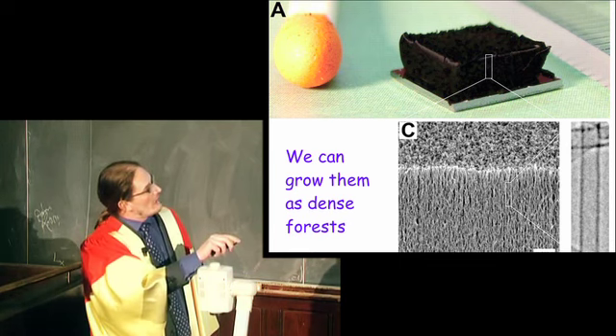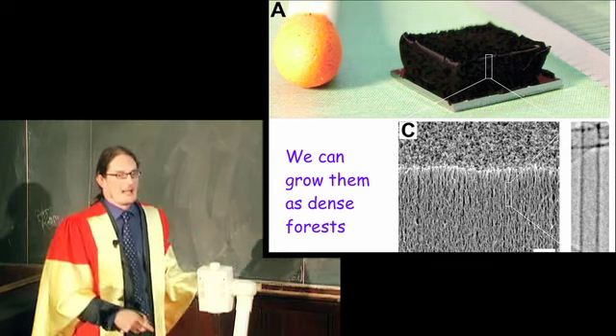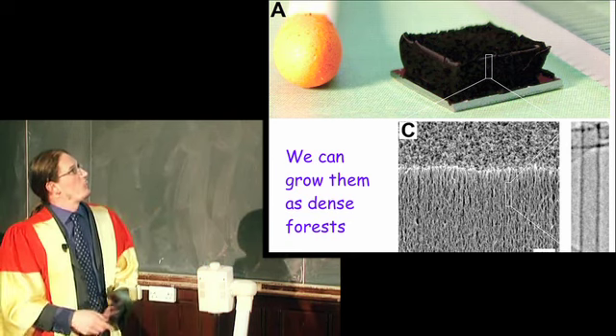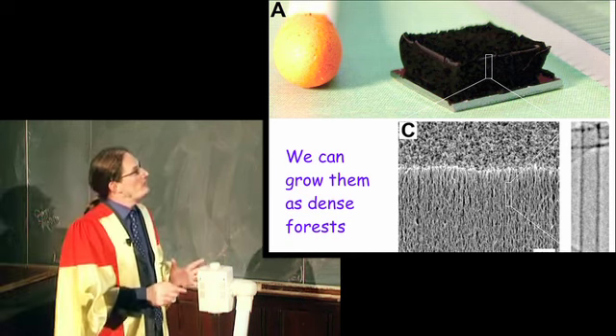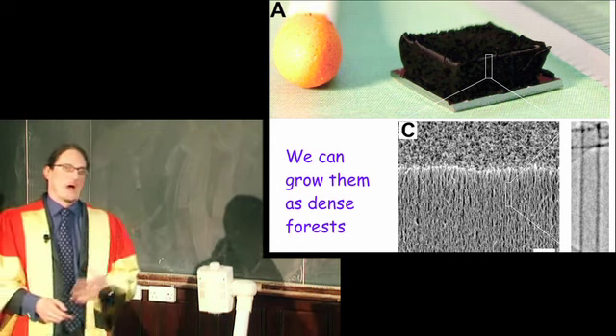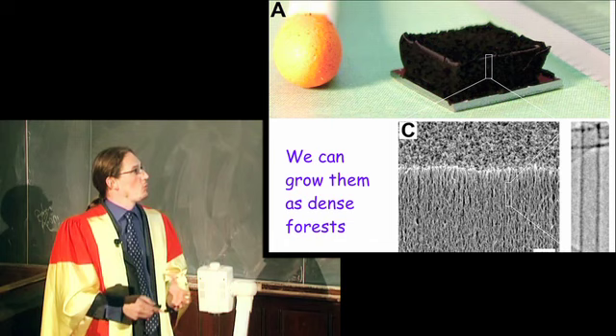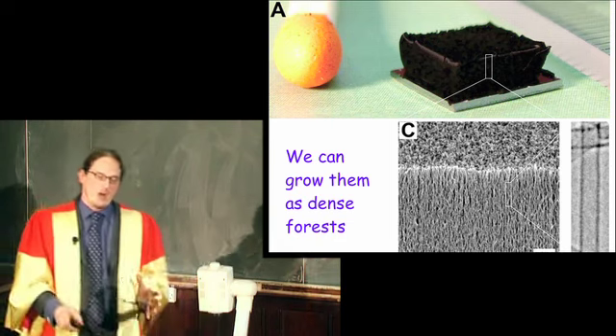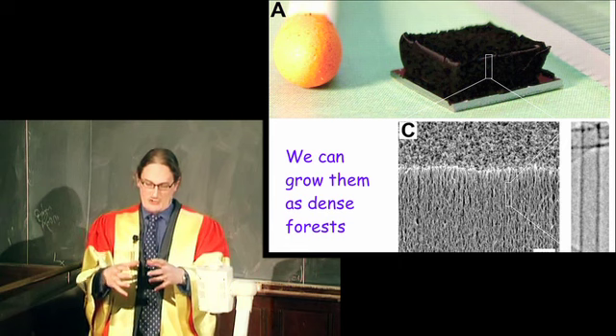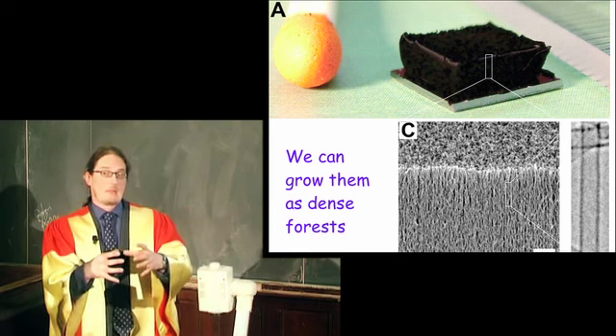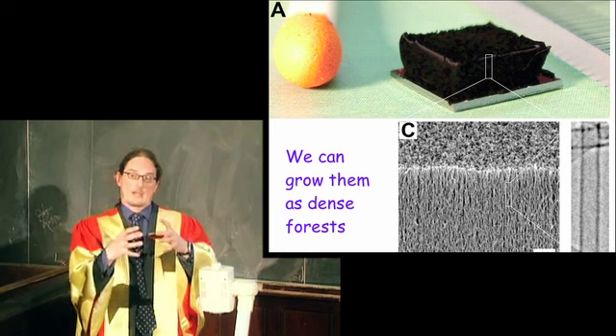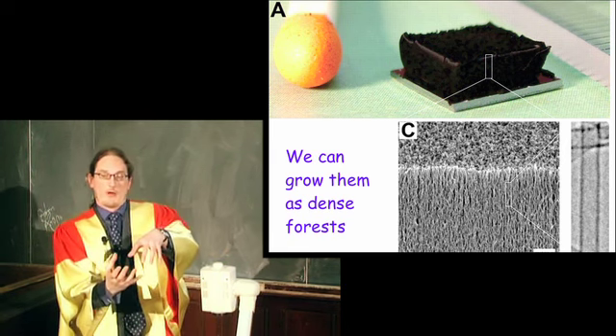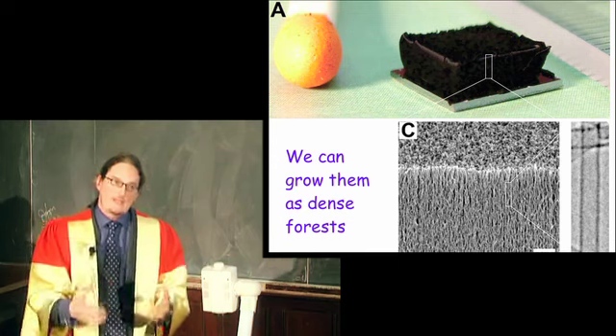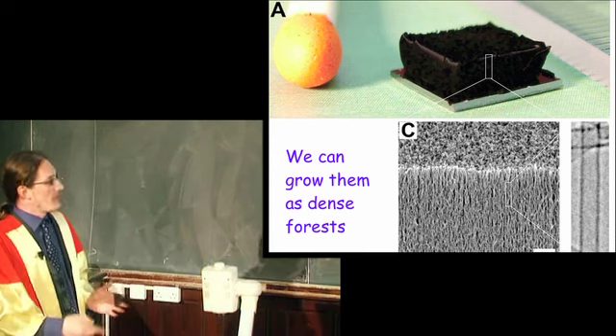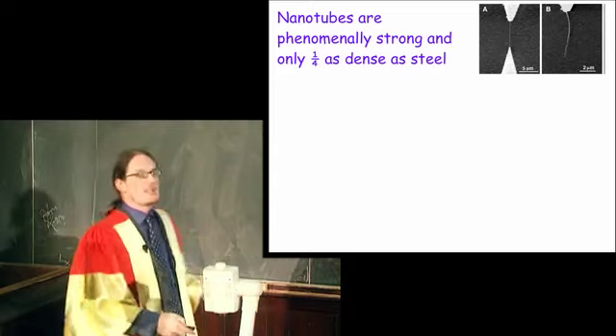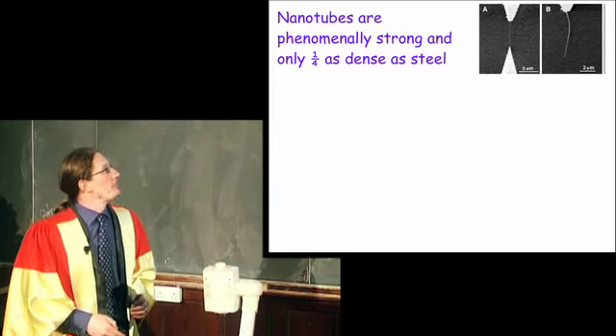Now, the diameter of that tube is about 2 nanometers. The length of those nanotubes is what? It's about 2 millimeters. This is what we call an aspect ratio, i.e. a length to diameter ratio, which is phenomenally large. And to put it in context, if I had a tube with the same length to diameter ratio that was this wide, and I held it like this, the other end would be in Manchester. So these things are really, really long and really, really narrow. They're the most elongated objects known to man.